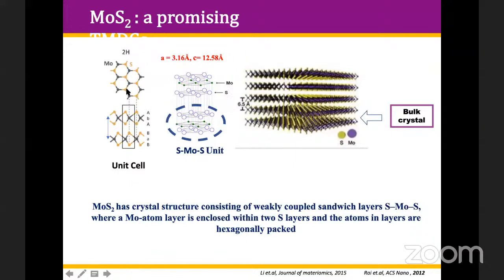If you go to a single layer, the structure is basically hexagonal. The unit cell is hexagonal here, and molybdenum is embedded between two sulfur layers, and this becomes one layer. The thickness of one monolayer is around 6.5 angstrom, 0.65 nanometer. Clear? Each layer, as we discussed, has covalent bonding in hexagonal form, and the layers are held by weak van der Waals forces. With increasing number of layers, it becomes the bulk structure. The lattice parameters are given here, 3 angstrom and 12 angstrom.